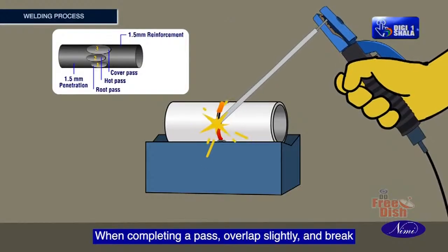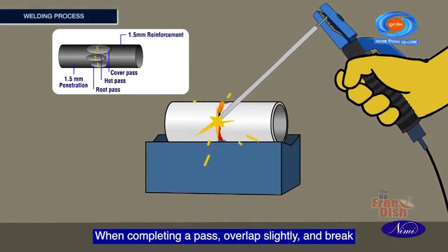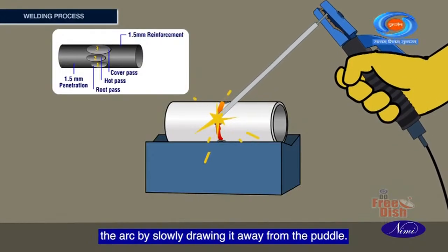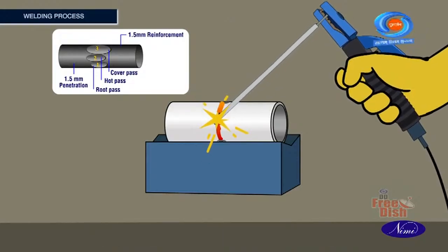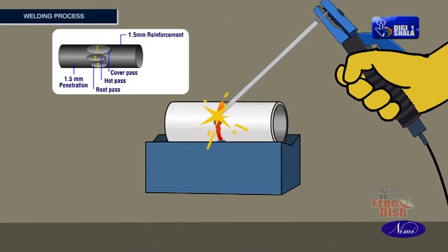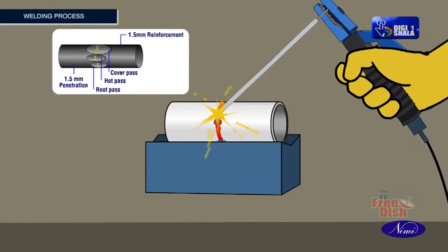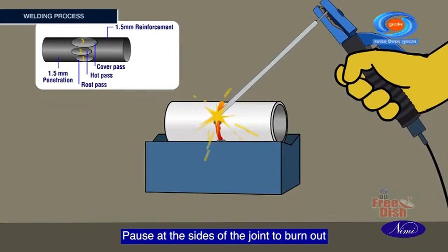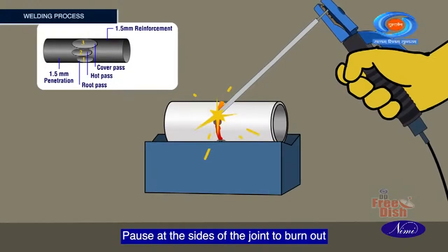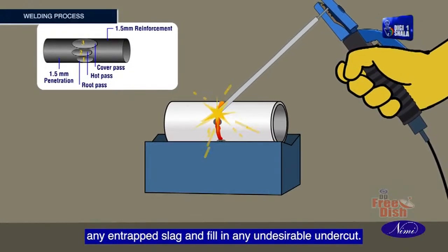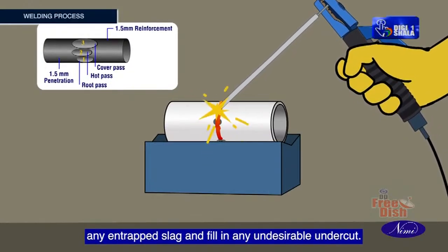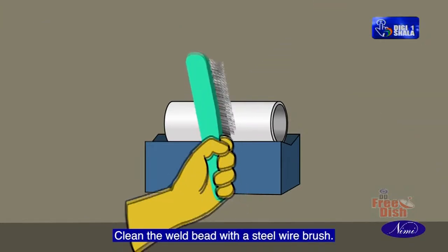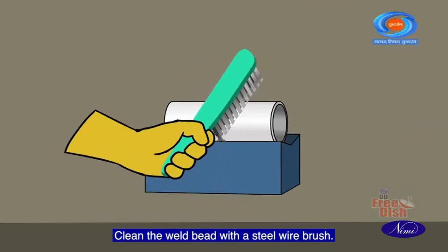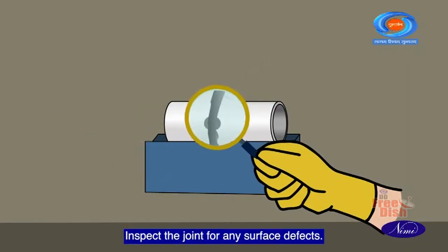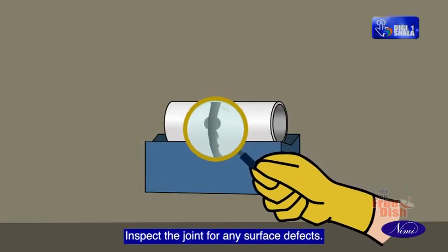When completing a pass, overlap slightly and break the arc by slowly drawing it away from the puddle. Pause at the sides of the joint to burn out any entrapped slag and fill in any undesirable undercut. Clean the weld bead with a steel wire brush. Inspect the joint for any surface defects.